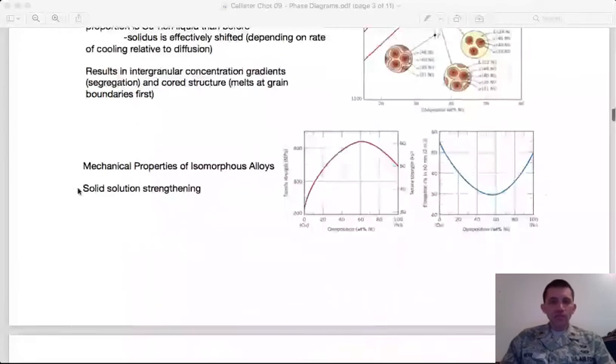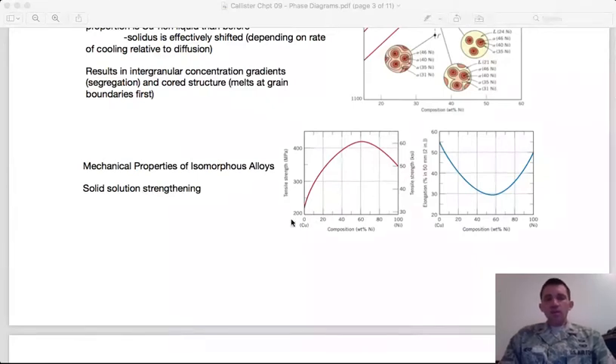Okay, so if you have a material like this, what are the mechanical properties that you can expect? Well, remember what happens as you start with a pure material and add in impurity atoms, right? Even if it's a good match like copper and nickel, it's still not perfect. And so putting a nickel on a copper atom site is going to disrupt that crystal structure, right? And then when I disrupt that crystal structure, like we saw two lectures ago, it's more likely that I will have a dislocation that co-locates with that impurity atom.